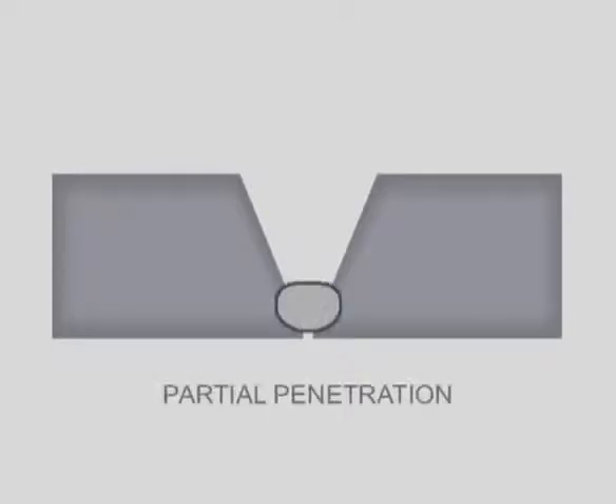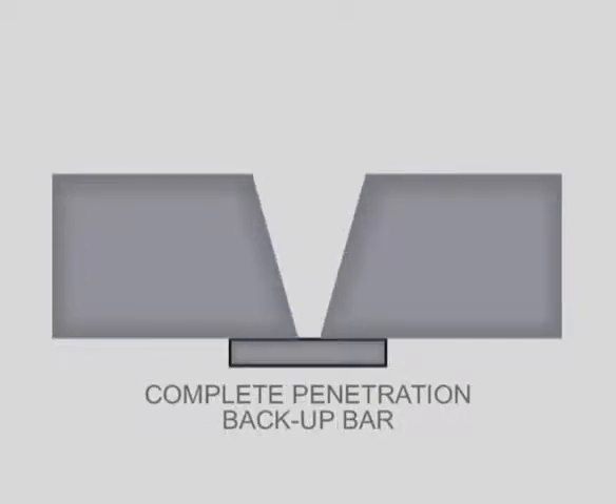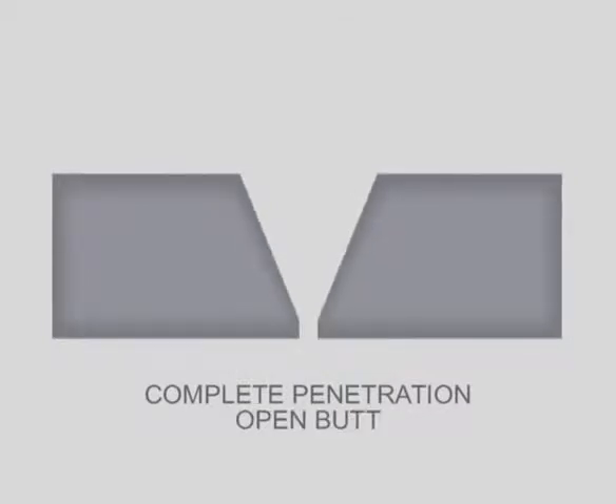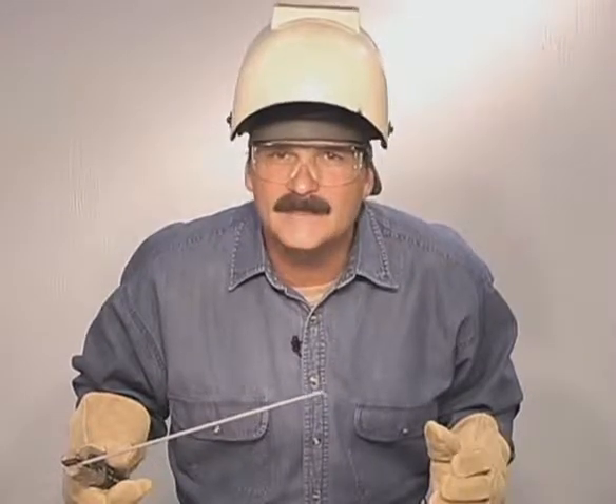The bevel pieces can be fit up with a small gap, allowing the first pass to penetrate as deep as possible. For 100% penetration, either a backup bar is used, with the first pass fusing all 3 pieces, or the metal is fit up with a gap, and the root fuses the bottom edge and actually builds weld on the back side. After the first pass, filling and capping is basically the same, so let's take a closer look at